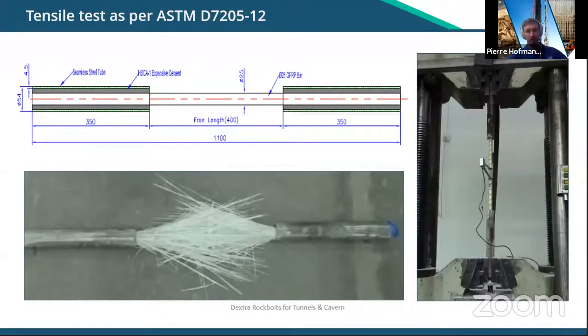However, the issue with GFRP material is it doesn't have linear behavior like you would get with steel. With steel, you can take a small piece, a big piece, cut a coupon out of it, send it to the lab, and then you characterize the grade of material. With GFRP, there's a size effect, we call it shear lag, and the big diameters don't have the same property as the small diameter, even though it's the same formulation. So we have to test the product in full section. We don't test a coupon of the material, we test the actual product.